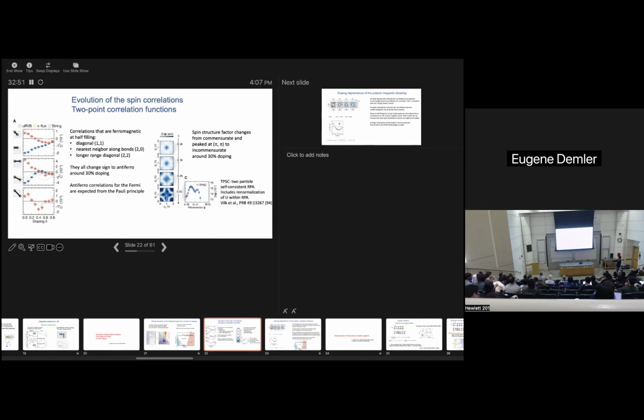One can then do a Fourier transform of the spin correlations. Close to half filling, one finds a peak at pi. That's the signature of antiferromagnetic order. Whereas for strongly doped systems, one finds four peaks. That's something that one would find by doing simple perturbation theory, like RPA. It's a way of resumming interactions. So again, the change from Mott-like behavior of correlations to something we would expect from what I learned from Fetter's book when I was a student here all happens around 30% doping.